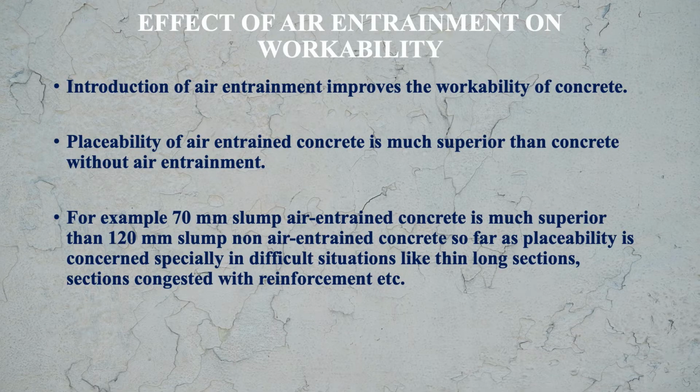the workability is increasing. Here we see that 70 mm slump air entrained concrete is much superior to 120 mm slump non-air entrained concrete. You know that the higher the slump, the higher the workability. But here you see that we are comparing two concretes.